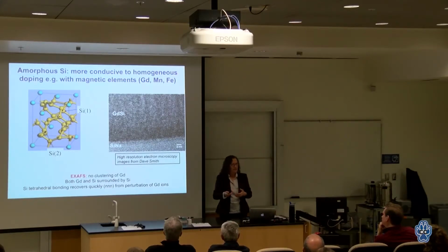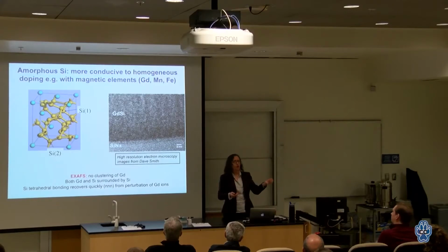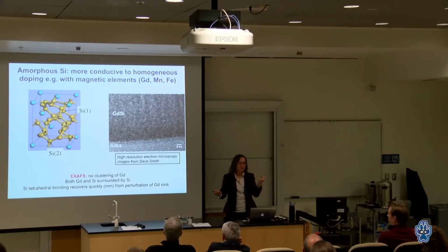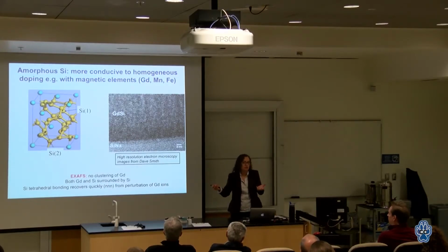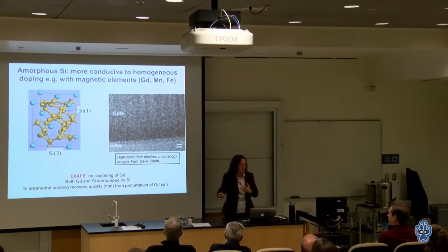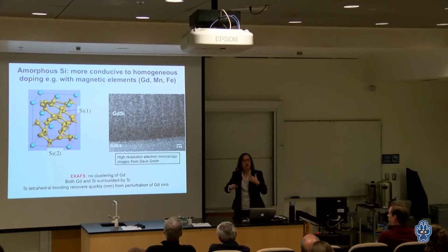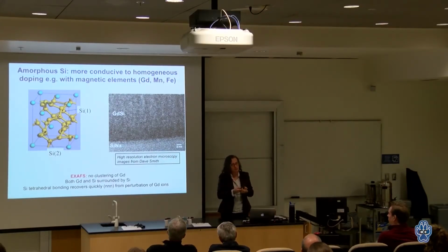Qualitatively, you can think of it as that in an insulator, the electrons don't move, so they have no kinetic energy. In the metallic state, they do move, and they have lots of kinetic energy. So you can think of an insulator as being driven by potential energy, the metal being driven by kinetic energy. This is obviously rather loose, but one can make this rigorous. The transition between the two is where the energies are equal. Anytime you have two energies that are equal, they're susceptible to being tipped. So all sorts of exotic physics happens around that balance, that competition between energies.